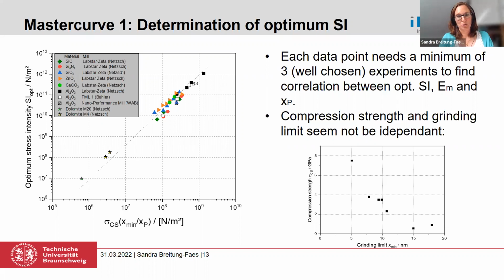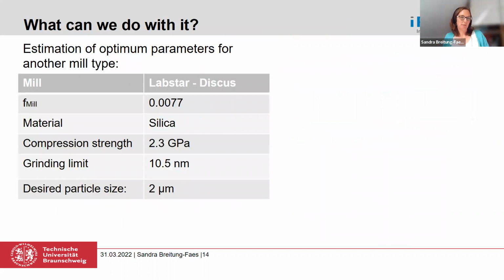There we used another way, which was shown by Knieke first. She said, okay, the grinding limit is correlated with the crystallinity or the crystalline structure of the material. And so it was able to calculate it. And this was realized here for most of the materials. And if you now compare at least the compression strength with the grinding limit of the material, you can roughly see a dependency of both of them. So if you say, okay, the compression strength I can find somewhere in the literature or on the internet, we can estimate the grinding limit out of it because it's connected. And now what we can do with it, well, we can calculate our optimum parameters.